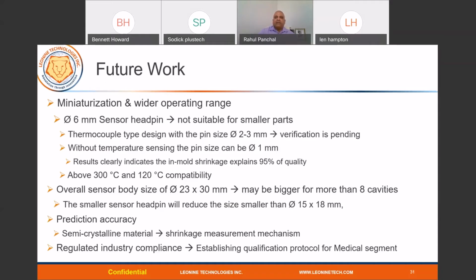And again, we see that for the amorphous material, 97% of the quality can be explained by the in-mold shrinkage alone. Then do we need the temperature sensing for them or not? If we don't, then we can reduce that pin size to 1 millimeter. So it can be very small. It can give you the pressure and the shrinkage, and you can use it at any temperature range, and you can still predict the part quality very accurately. You can still use the smaller part, and then you still don't have that resistance of using a new technology.